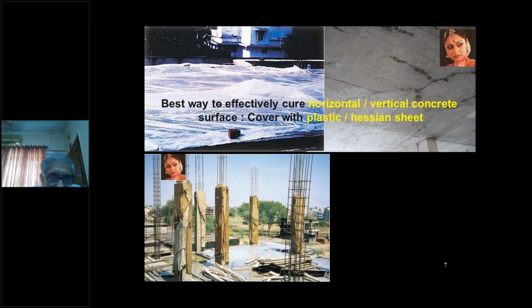Whenever the structural member has a bigger area compared to its volume, these cracks are known to be seen everywhere in all parts of our country. Even where there is high humidity, even where there is low humidity, even where temperatures are low, even where there is no wind, these cracks occur. So we recommended the client who was blaming our cement, when I was working in Ambuja Cement, to put a plastic sheet.